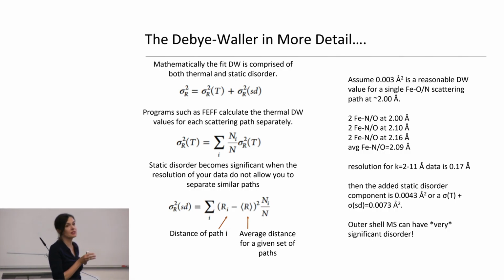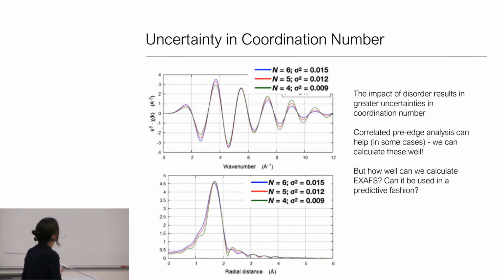I don't want to go through this in detail, but just to point out that this is something that can really put uncertainty in the Debye-Waller terms. And basically, just to bring this point home, if I vary the Debye-Waller and vary the coordination number, as the Debye-Waller actually gets smaller and the coordination number, you can basically just see that it's an underdetermined problem because these two things are fully correlated with each other.